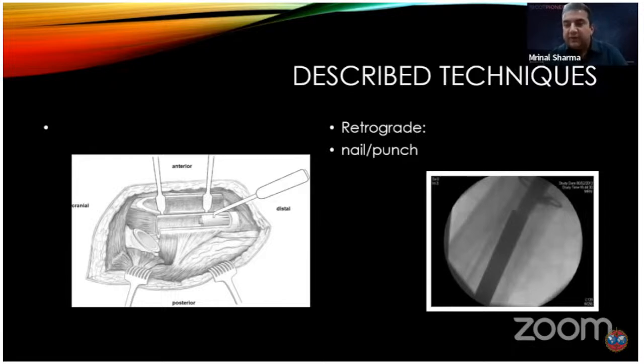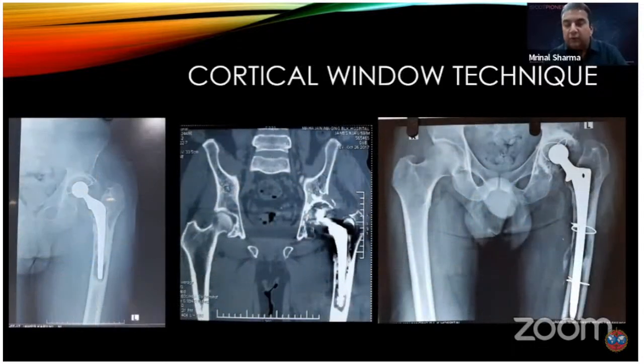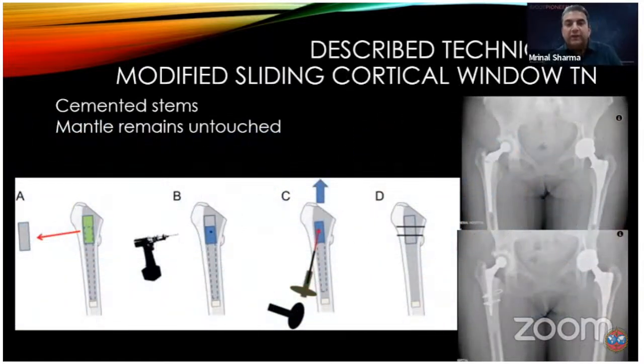Another technique has been described where the stem might be loose in some cases, and you can hammer it out with a punch or a retrograde nail through the knee, and the distal tip can be punched out in a retrograde manner. A cortical window technique is often used by us for revision, where the distal fitting, the cement or the pedestal, is hammered out through this cortical window. This is not a broken stem, but a similar technique has been used, which is called the modified sliding cortical window technique. It is used for cemented stems.